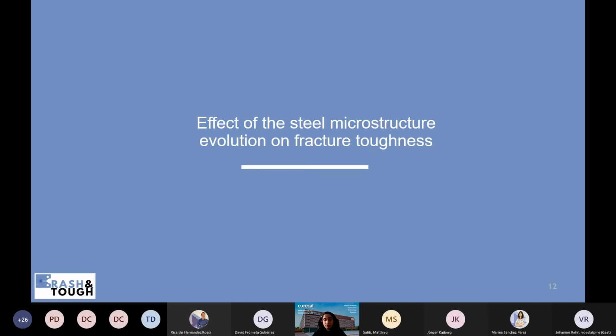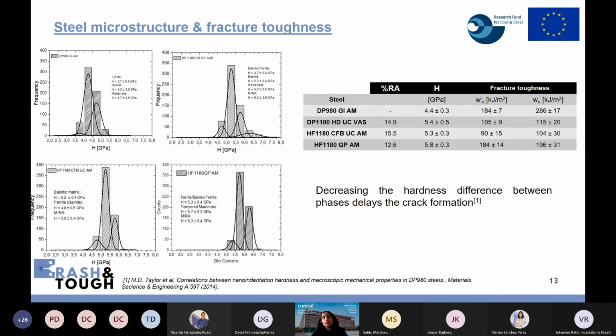So, how do these mappings and microstructure affect fracture toughness? Directly from the hardness mappings, we can extract a histogram and analyze in an approximate manner the hardness of each microstructural constituent present in the microstructure. Here we have all four steels, and we can observe that if we decrease the hardness difference between the phases, the crack formation is delayed.